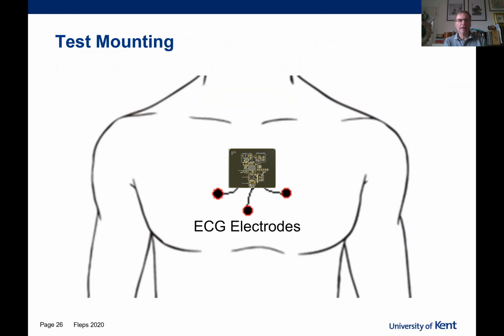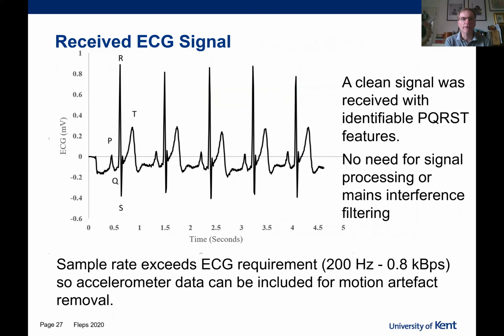So the test for the actual ECG signal itself: the test circuit was mounted on a volunteer's chest. In this case, we used clinical electrodes, so this is using a wet electrolyte gel for the first test, and relatively short leads, so the electrodes were not placed far apart from each other. The slide here shows the recovered data over the RFID link, and it can be seen that it's actually quite a good quality signal.